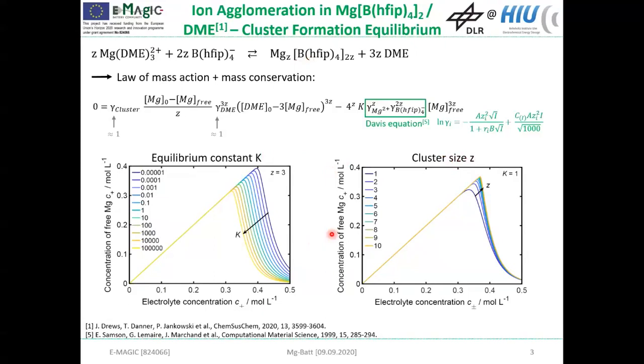And thereby, the cluster size has only very small impact, whereby the equilibrium constant K more significantly influences this critical concentration. But although we analyzed a wide range of values for K and Z, the critical concentration is always here in this range, which is exactly the range that the experiment has a look at.